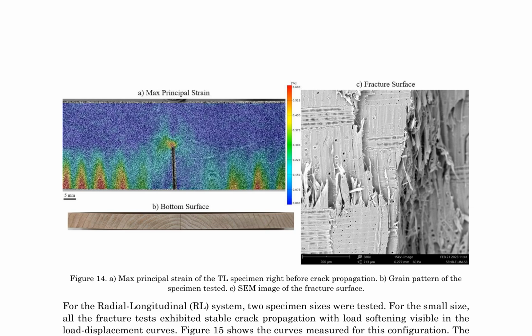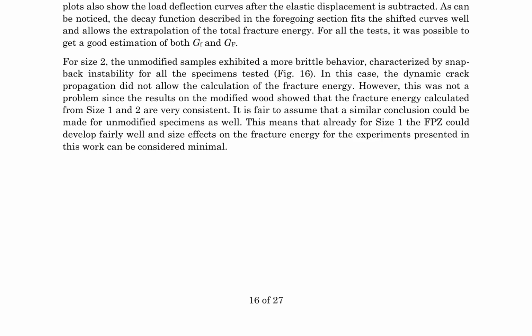The load displacement curves for the RL system exhibit stable crack propagation with load softening, allowing for the estimation of both the initial and total fracture energies. The decay function fits the shifted curves well, enabling the extrapolation of the total fracture energy. In contrast, the larger size specimens exhibit a more brittle behavior, characterized by snapback instability, making it challenging to calculate the fracture energy. However, the results suggest that size effects on the fracture energy are minimal, and the fracture process zone, FPZ, can develop fairly well even for smaller specimen sizes.